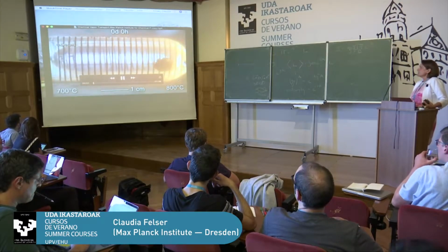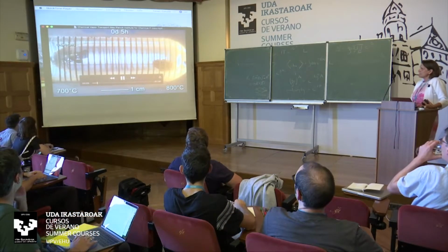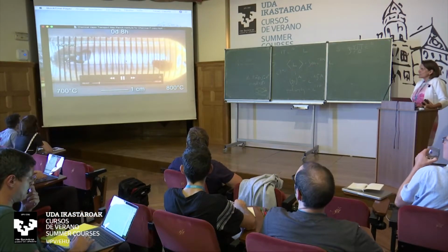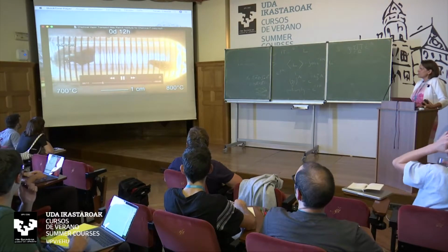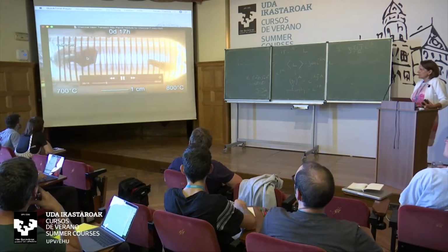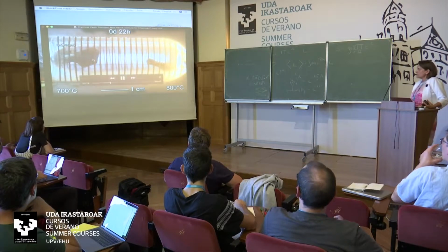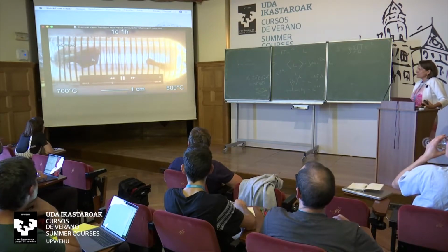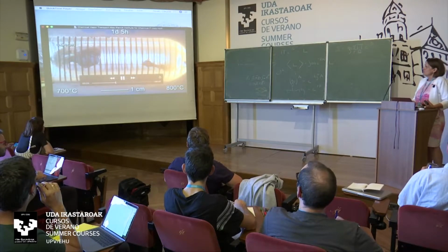Okay, so you take polycrystalline samples, and then you put it in a temperature gradient with some iodine, and here you see how the polycrystalline sample shrinks, and I hope you see the single crystal here growing. And it grows, and at a certain point you should stop, because sometimes you have problems and it reacts with a wall, what you see here.